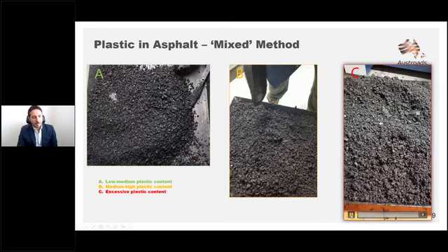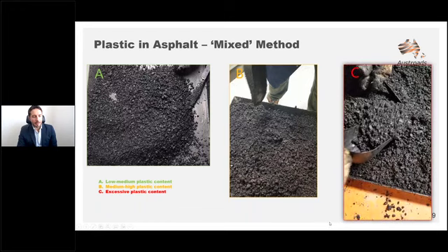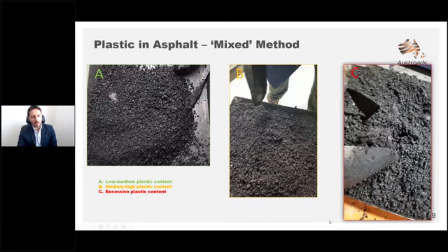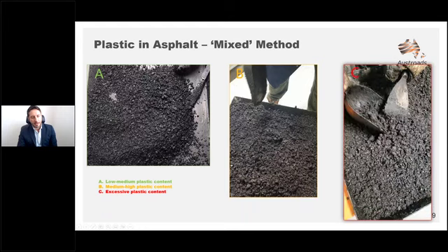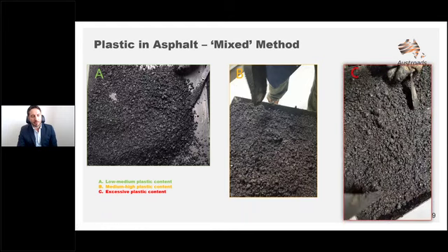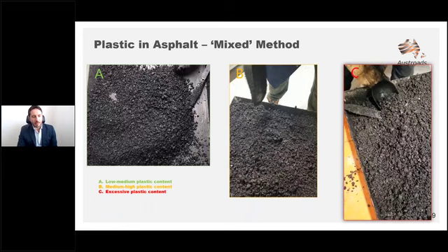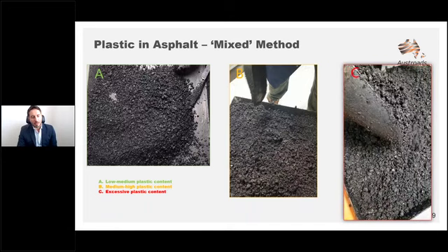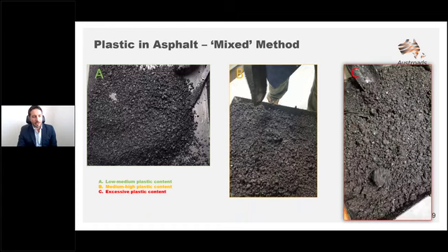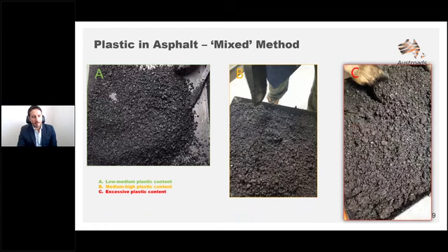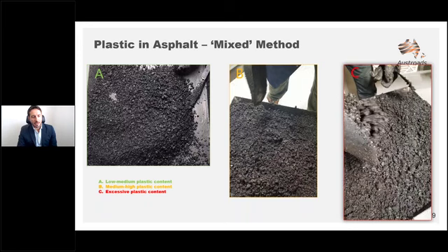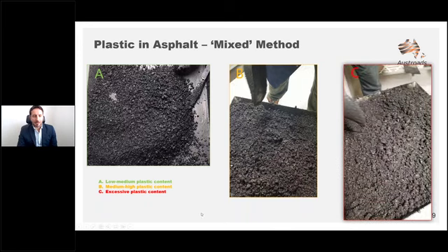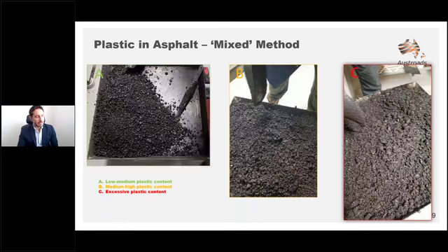The last video here, number C, is related to an excessive plastic content, and this is exactly that 2% mix that I showed you before in the previous slide with the red curve. You can see that actually you cannot really work with that at all. You have big chunks of asphalt, so it was quite difficult to handle. Just to give you an idea about the different dosages and how they translate into compactability or into the densification